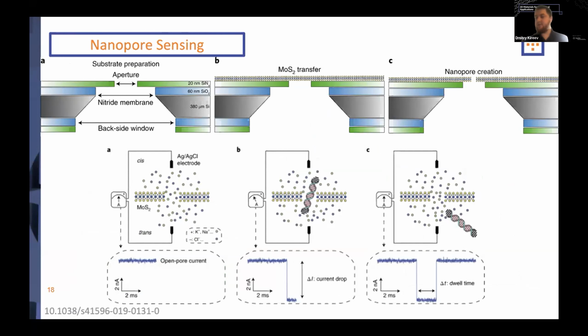Another very big field of 2D material sensing is so-called nanopore sensing, where you can create 2D material-based nanopores. Right now, very common nanopores are made of silicon nitride. So you have an aperture of 20 nanometers made of silicon nitride. You would transfer MoS2 on top of it, and then shape the MoS2 so you make a very tiny opening in it. Then, by applying, I believe, an electroosmotic force, and having DNA in the solution, you can drive the DNA molecules through these nanopores while recording the electrical current, the open pore current, through the nanopore of 2D materials.